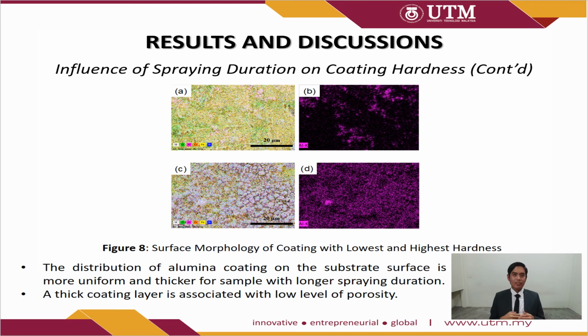However, if the spraying duration is shorter, there will be a presence of unmelted particles and pores inside the coatings as shown in figure 8B, therefore leading to a weaker coating bonding strength. Lastly, the Vickers hardness values will decrease as the level of porosity increases.